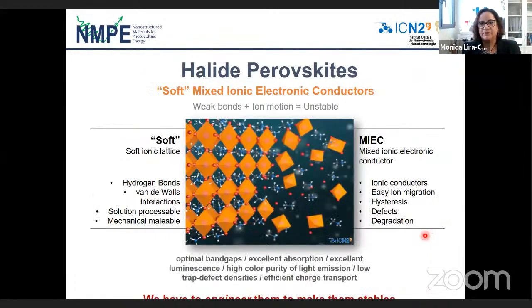So with this idea in mind, I want to tell you that halide perovskites are not classical semiconductors like silicon or inorganic semiconductors. These are soft mixed ionic electronic conductors. This soft nature is what makes halide perovskite able to be processed in solution and made into flexible devices, which is very positive for our technology. However, soft also means weak bonds, and this ionic electronic conductivity means you have ionic motion. This ionic motion is what makes halide perovskite solar cells unstable. So what we have to do is engineer these ions.